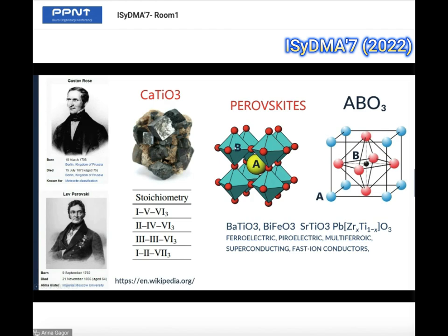The metal ions at the B sites are octahedrally coordinated, and these octahedra form a 3-dimensional substructure connected through the corners. In this substructure, we have larger cavities, which may adopt larger cations.